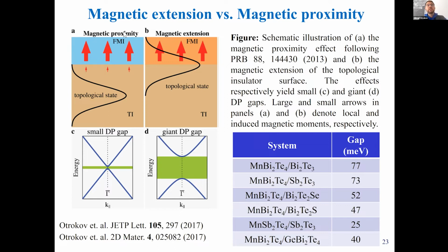Well, if you wish, I will extend a little bit. GGA plus U, we found that it works pretty reasonably for manganese bismuth telluride in bulk. What I mean is that we have been able to predict correctly both magnetic ordering, magnetic anisotropy, and critical temperature, based on the ab initio input, bulk bandgap. So I believe this is quite convincing, and we can use GGA plus U. We apply Hubbard U on the 3D manganese states.